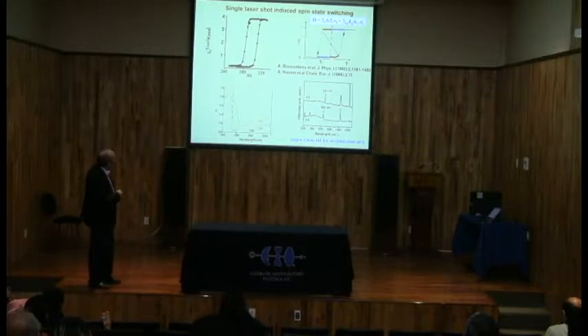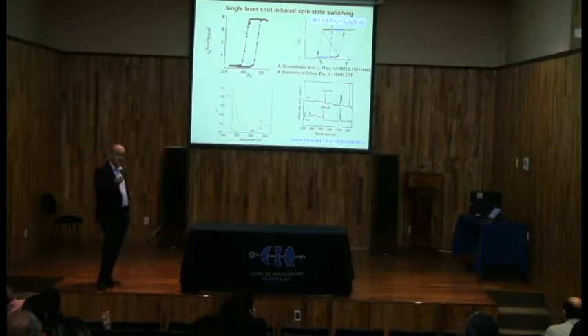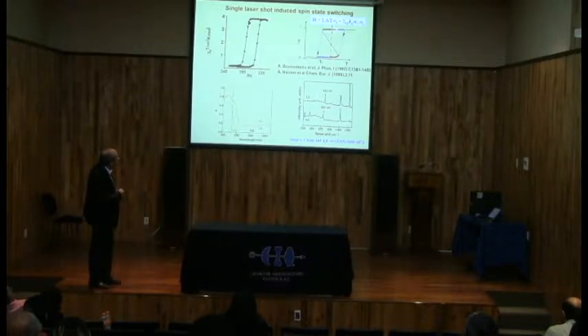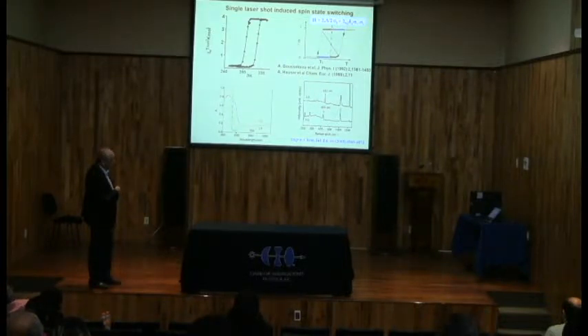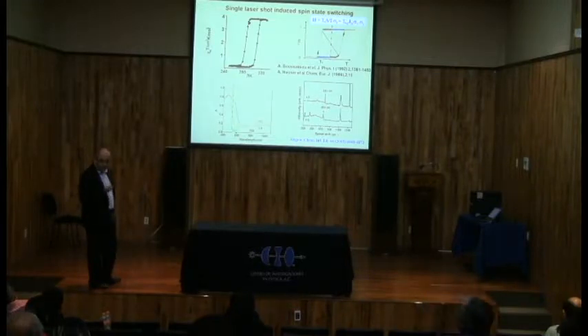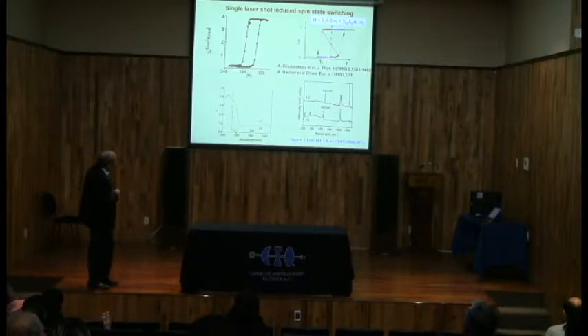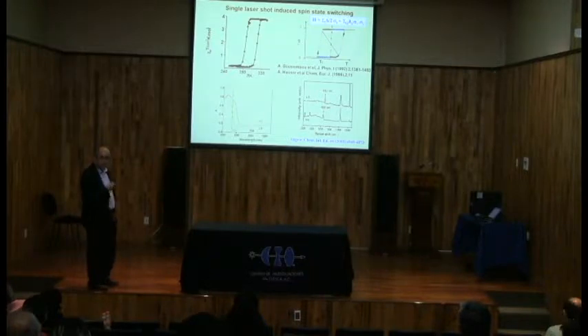That means if you are in a metastable state and you find a way to give energy to your system, you expect to switch it from the metastable to the stable one. If you are just around the critical temperature, metastable in the high spin form, and you can find the right energy to give to your system, you can switch from the metastable state to the stable one. In theory, you can go from spin 0 to spin 2, and from spin 2 to spin 0, reversibly around the critical temperature. So this is the theory.